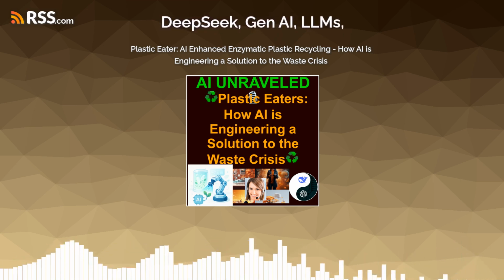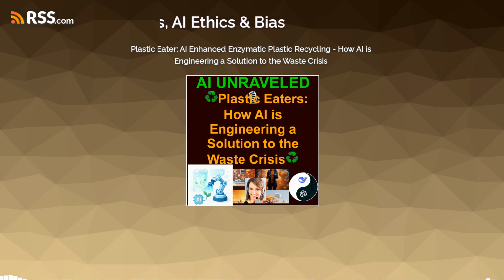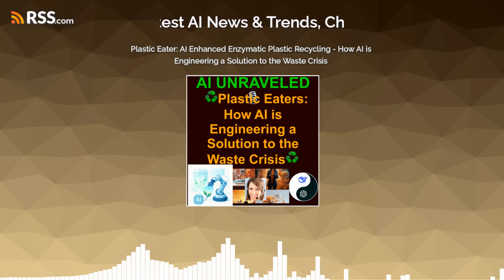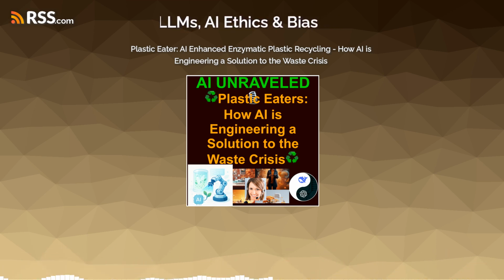And crucially, it works efficiently at temperatures below 50 degrees Celsius. That's a big deal. Yeah, it hugely cuts down the energy needed compared to processes requiring high heat. And it might even open the door to using it for environmental cleanup, where you can't easily control the temperature. Lower operating temps mean lower costs, lower energy use, and potentially broader applications. It's a win-win-win. It's also effective on a whole range of PET products. Clear, colored, stuff from containers, fibers, fabrics, those ubiquitous water bottles. Versatility is important for real-world waste streams.